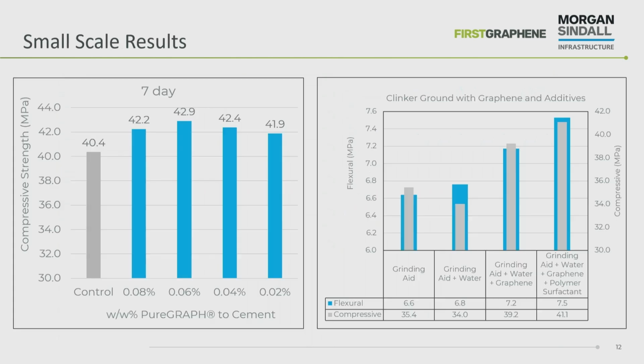I won't show you all the data, but we saw decent trends in the data. So at early ages, you can see here where we're looking at, firstly, the graphene loading on the left. So how can we optimize for graphene loading? You can see it goes up there. So you add graphene, and then it reaches an optimum. We found this in literature as well with our materials.